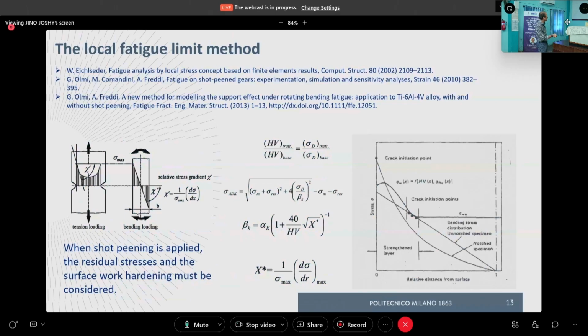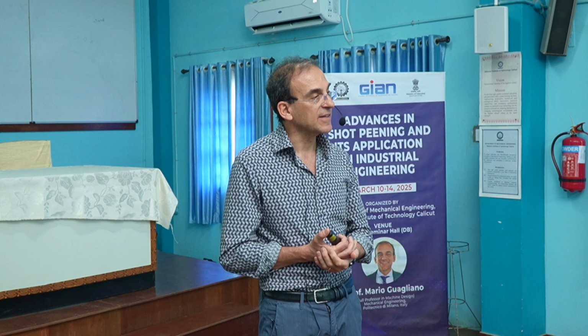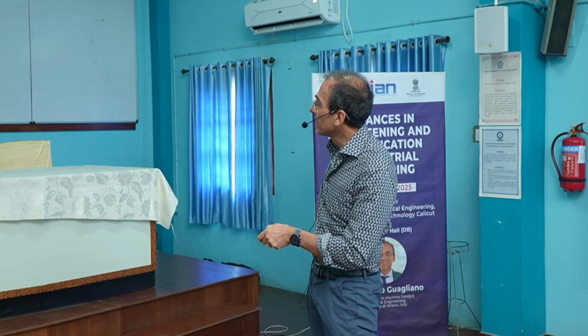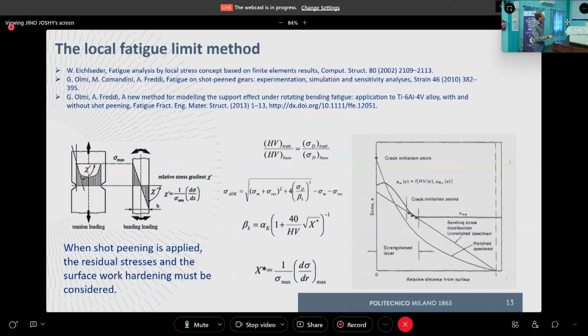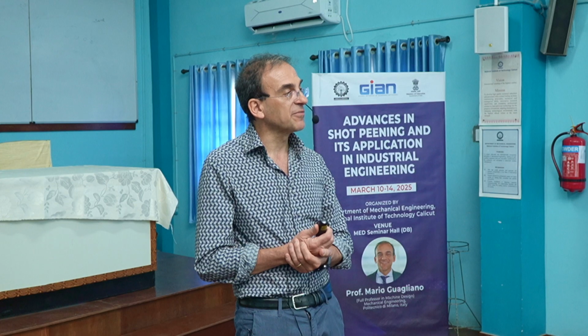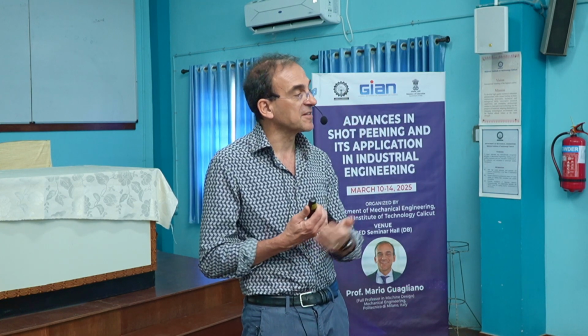So in this representation, where the point is here, we are going to have a fatigue failure for sure. We see that whatever the notch is, if we have a notched part, this failure will start from the surface. This is the first point that will intersect the local fatigue limit. The same is not happening if we consider a smooth part. This is linear. We start from this condition, we increase the load, and at the end, the first point that intersects the curve that defines the local fatigue limit is not at the free surface, but is internal.